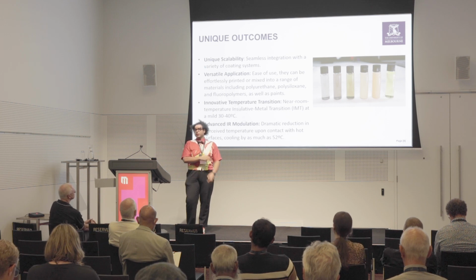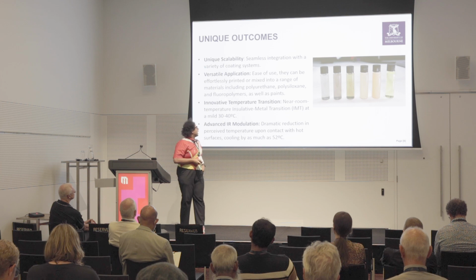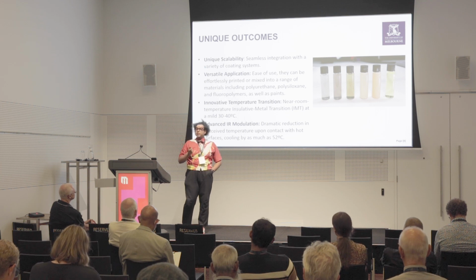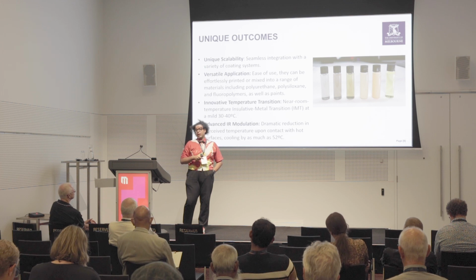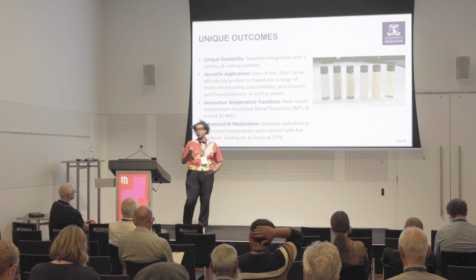You just change the pressure of the chamber, and that changes the entire bucket of nanoparticles. And the other thing is the thickness of the silica shell itself is another control. So we open the toolbox to have more ways to accomplish that low transition temperature without changing the compound itself too much.